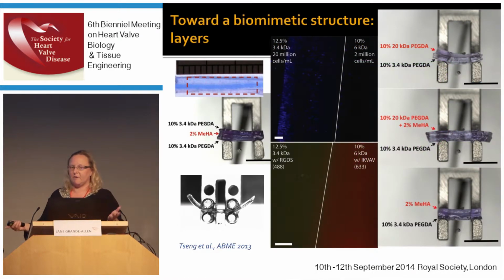Since I love biomechanics, we've been trying to move towards a more biomimetic structure for these hydrogels to have. And one of the things that was impressed upon me when I was doing my dissertation by Karen Kunzelman was that it's important to replicate the bending mechanics of heart valves. And one of the reasons that they have unique bending characteristics is because they are softer in the middle. And so we've been working really hard towards getting a layered structure.